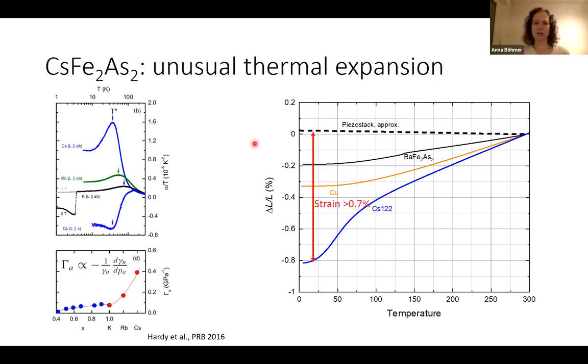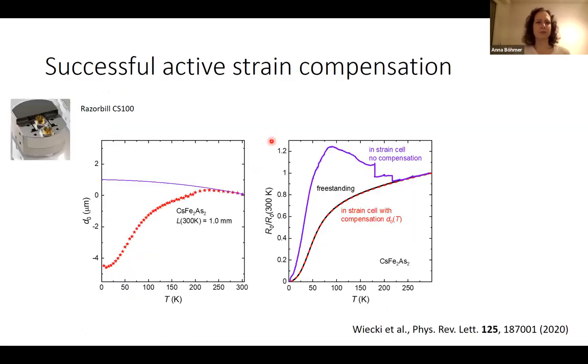So a sample on a piezo stack would already experience a huge amount of isotropic strain. So we thought it might not be the best idea. And instead, we use a Razorbill strain cell that was also just introduced to compensate for this strain mismatch. By moving the 2 sample mounts closer together on cooling, which would be these red stars here, we can keep a sample in a strain-free state within the system. We see that the resistance follows the one of a freestanding sample. If we don't do that, we break the sample or change the state dramatically.